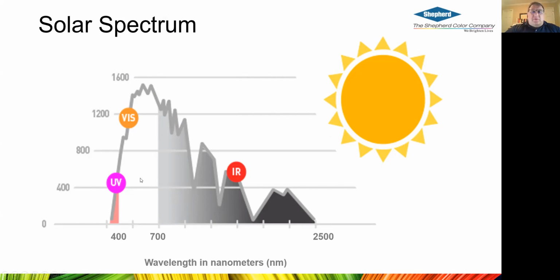So the sun is not just putting out light for us to see, it also is putting out a lot of energy from around 295 nanometers all the way out to 2500 nanometers. And if you integrate the area underneath these curves, you can find that there's a few percent in the UV, although it's very damaging. And roughly the rest of the sun's energy is split between the visible wavelengths and the near infrared. So the key is that we can't perceive these near infrared wavelengths. These are invisible to our naked eyes.